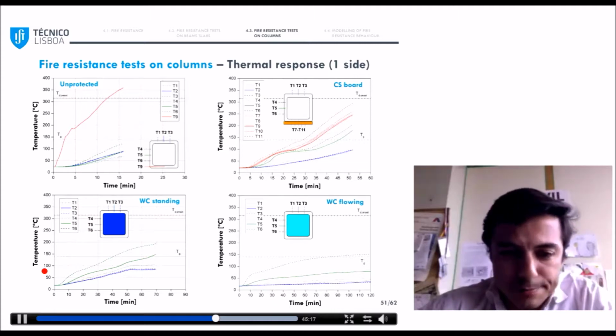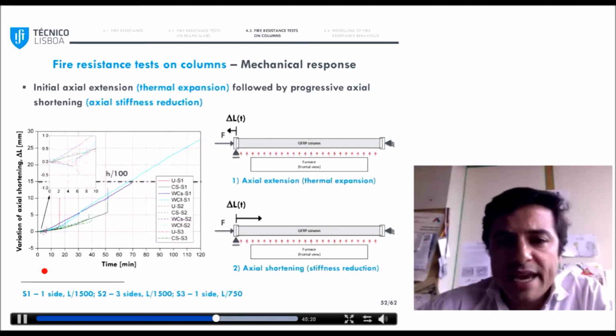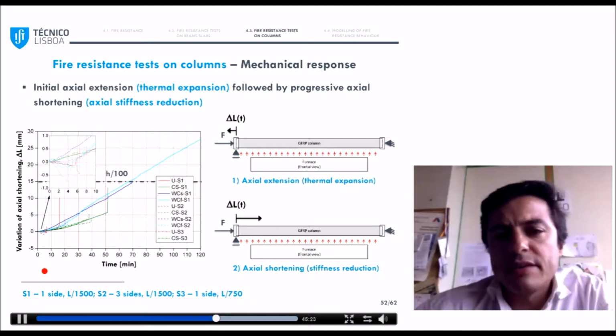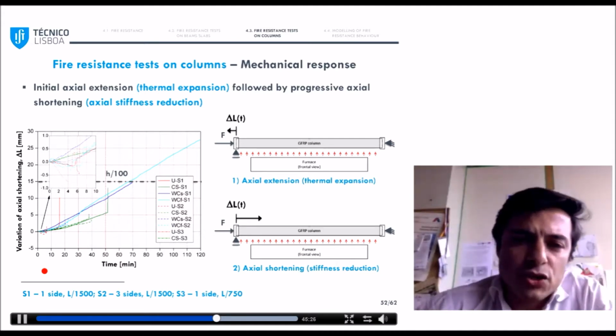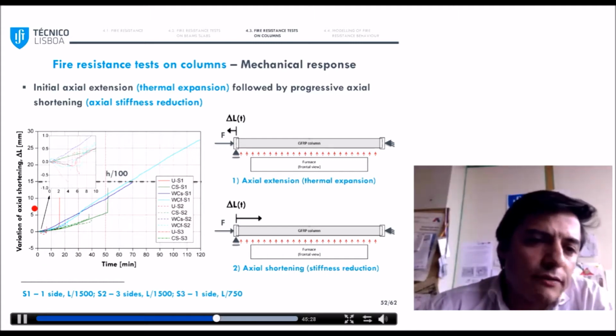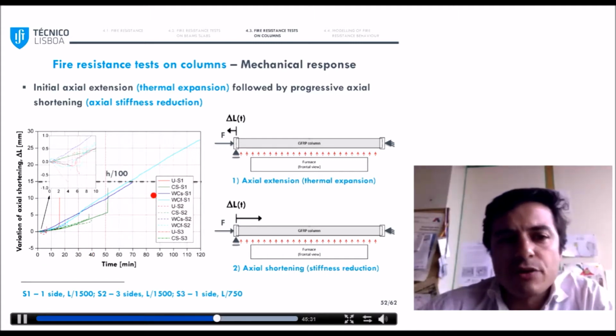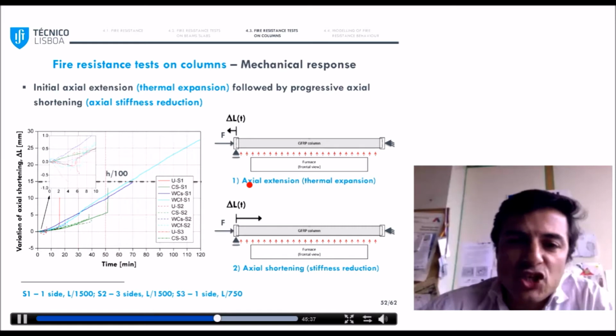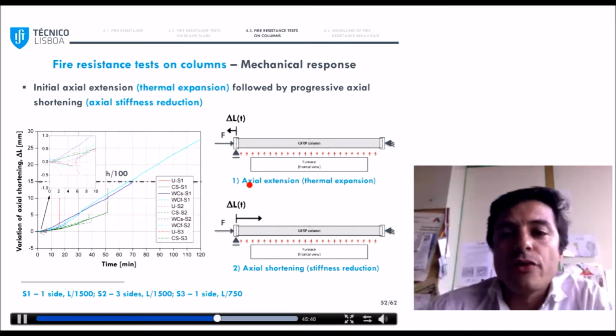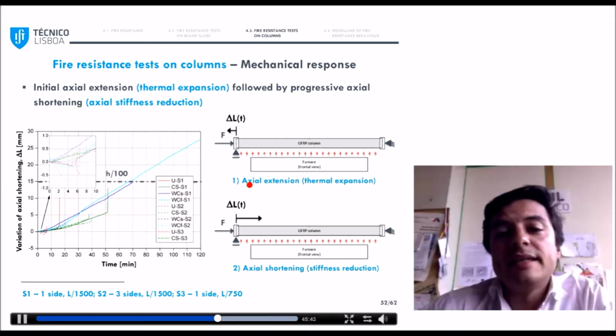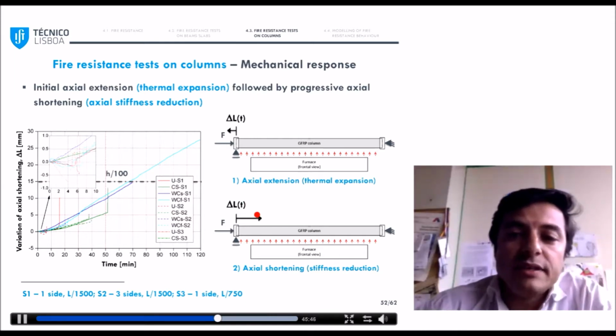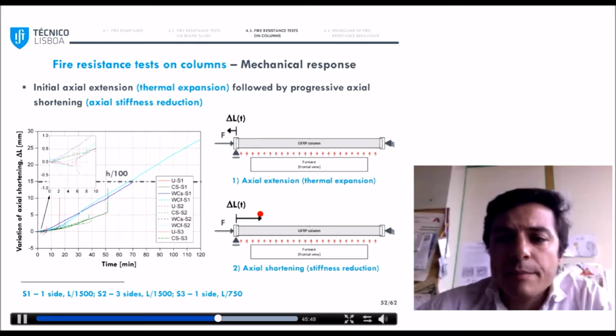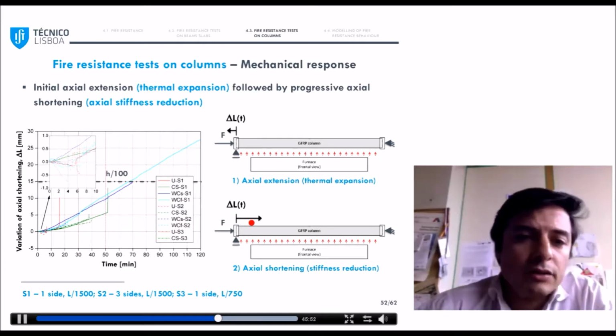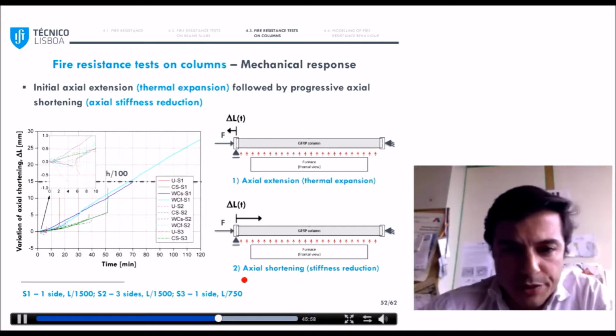And with this, we were able to keep the top flange and almost the entire web below Tg for 2 hours. In terms of mechanical response, which is quite more complex than that for beams, this picture shows first the variation of the axial shortening as a function of time for the different columns. In some cases, there was a slight initial axial extension due to the thermal expansion effect, and this was then progressively succeeded by an axial shortening of the material due to the stiffness reduction caused by heating and, of course, due to creep of the material.